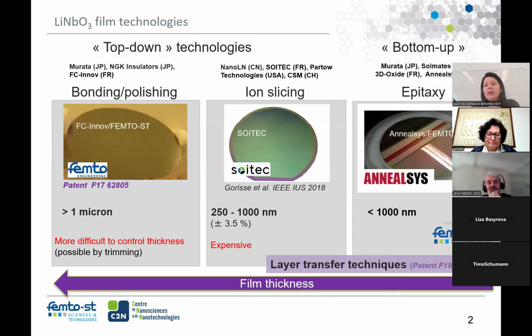This becomes a little bit more complicated when we need to go down to thicknesses below 1 micron. It's still possible because we have trimming techniques, but it's difficult to control the thickness precisely. And another thing, we use a complete wafer to make one single film. So these are limitations, but the main limitation, I would say, is thickness control. It's a very good method for making thick films because we get single crystal quality films. Even for thin films you can do it, but then you need to do a lot of trimming to reach homogeneity of the thickness.